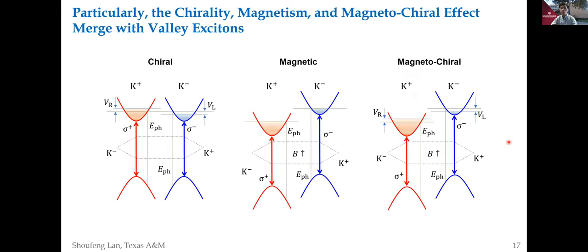As a typical transition metal dichalcogenide, or TMD, WS2 has two degenerate valleys in its band structure. For the chirality, it will induce a population difference in the two valleys, K plus and K minus. For the magneto-optical effect, it will induce a shift of the band structure and also lift the degeneracy between those two valleys. For the magnetochiral effect, it's a combination of the two, but later I will show you it's not a simple superposition.